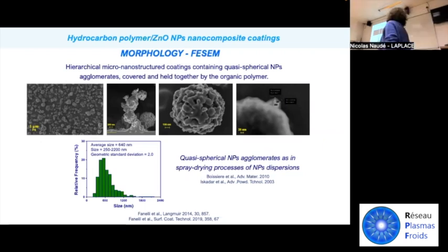The formation of quasi-spherical nanoparticle agglomerates is expected in principle, because it is widely reported in the literature on spray drying processes of nanoparticle dispersions, where it has been widely demonstrated that typically the evaporation of the solvent leads to the formation of these micro-nanostructured spherical agglomerates.